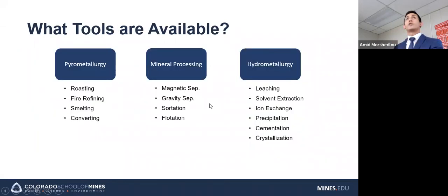Ideally, we would like to do some sort of pre-concentration with mineral processing. That is going to be a little bit difficult in this case, because the slag is amorphous, which means there's no long-range crystalline structure, and so no long-range order to give us predictable properties that we can take advantage of for mineral processing. So there are two ways we can get around this. One is to grind it really, really finely to take advantage of any potential short-range properties. Alternatively, we could heat it up, get some solid-state diffusion going, and devitrify it, or make it crystalline, so that there are properties that we can take advantage of on a longer order.